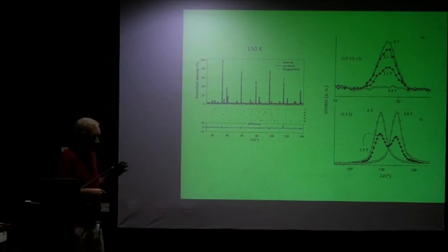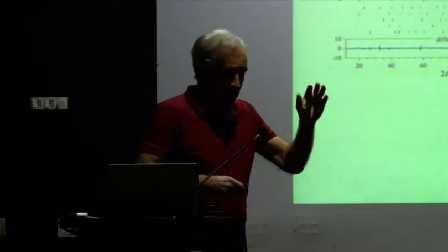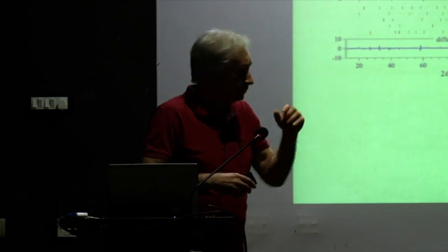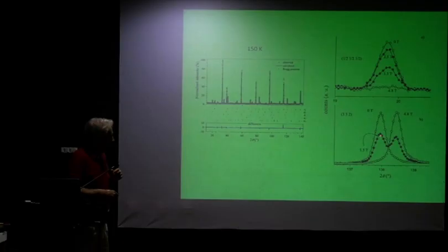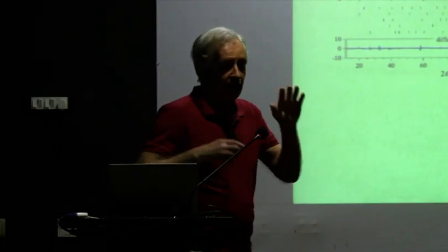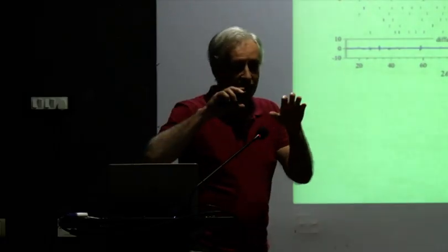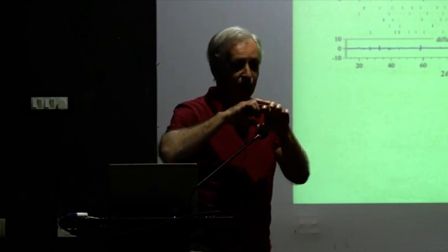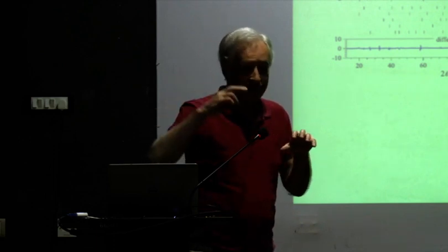But we see that the volume associated with the antiferromagnetic state is causing a drop in the intensity as we're increasing the field, and another one is coming up. So we have small volume states and large volume states coexisting with one another in this transition.